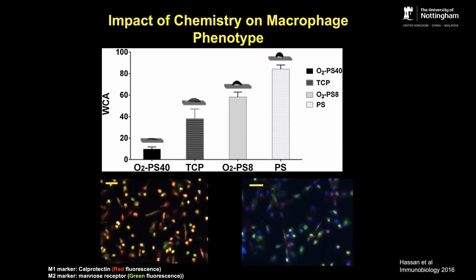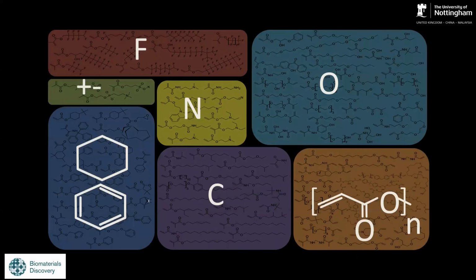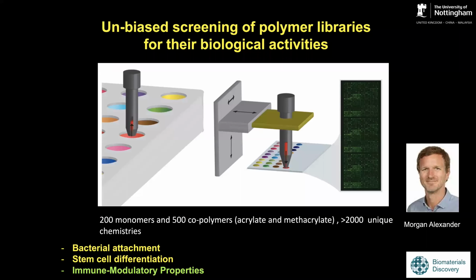So we have characterized these cells a lot more, and actually the surface phenotype also goes with the cytokine profile and other properties. This gave us motivation to expand this search to other chemistries, looking at a wide range of different chemistries and seeing how they could influence macrophage polarization. And that's where we started working with Morgan in Nottingham, who had previously done quite a lot of work using these polymer libraries for looking at bacterial attachment and stem cell differentiation. It is a relatively straightforward technology where you can create diverse libraries of acrylates and methacrylates, and then look at cell behavior by seeding cells in a semi-high throughput manner. So we wanted to apply this to macrophages in the first instance and identify chemistries or polymers that are able to influence macrophage polarization.